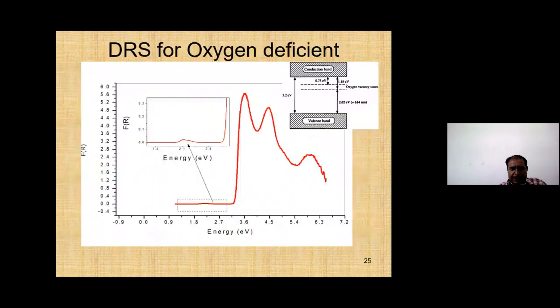So let us see, this is the optical absorption spectra of one of the samples having oxygen defects. These particular peaks are essentially due to the electronic structure of that particular material. This particular drop in the optical reflectivity corresponds to the band gap. And then there is one more peak you can see here, and what we claim is that this particular peak is essentially due to the oxygen defect which may be present in our sample. In fact, we have deliberately produced the sample with the oxygen defect.